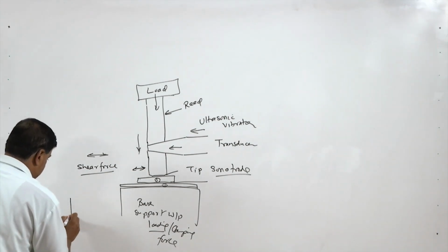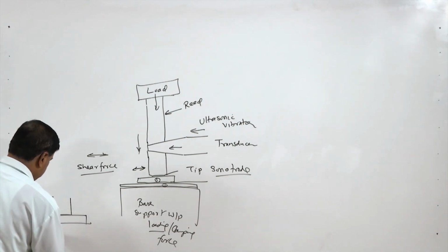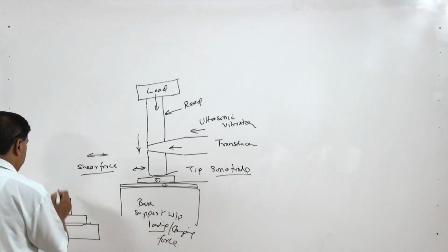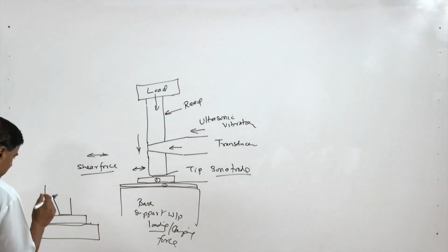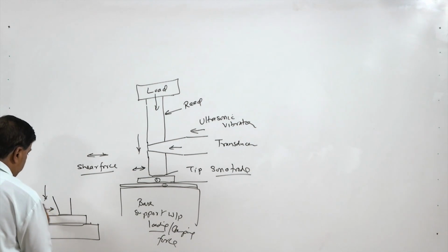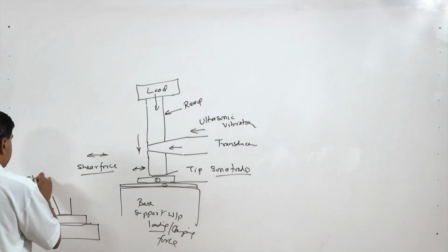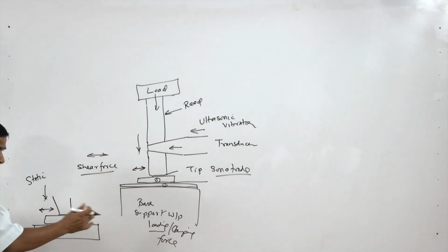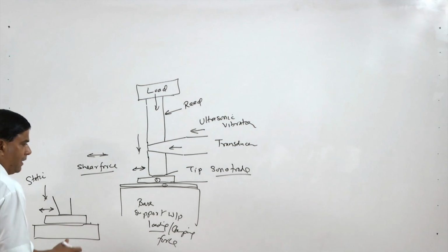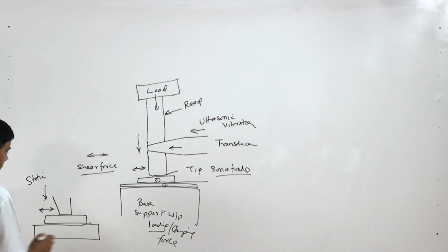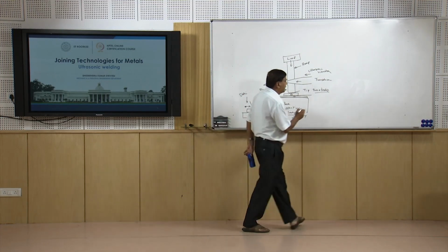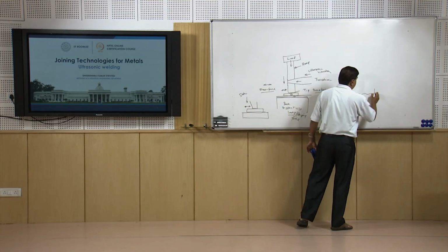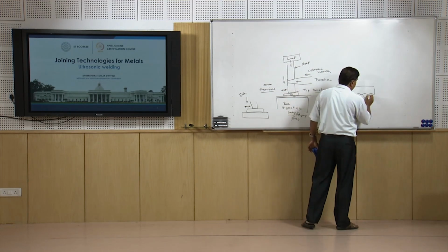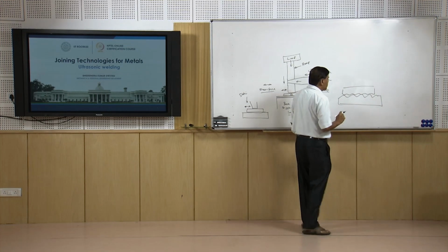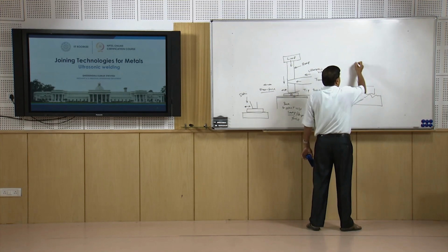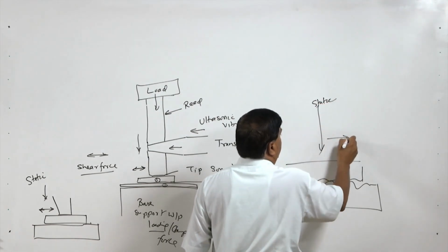So, the tip basically applies a combination of compressive clamping force and shear force. The clamping force is static in nature, while the shear force is dynamic, acting laterally at a very high frequency. So, when there is direct metal to metal contact, like say this is the real surface of the upper component and the real surface of the lower component, having contact at peaks and valleys under the constant static load and the lateral shear force,